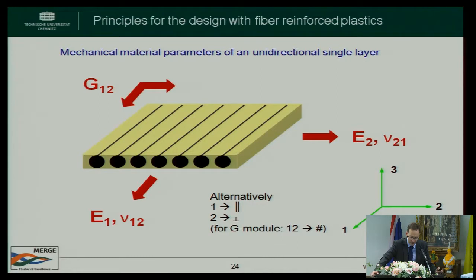So it's not an isotropic material, it's an anisotropic material. And as we know from steel, we have one tensile modulus, we have one shear modulus, and depending on the kind of steel, we have different strengths. But in all directions, the same strength. So typical for steel, we have only one tensile modulus. So tensile modulus for steel, all should more or less know. We have 210 gigapascal tensile modulus. For the strength, it depends on the sort of steel. Let's say 350 MPa for normal stainless steel, can be higher, up to 1000 megapascal for high strength steels, but that's it.